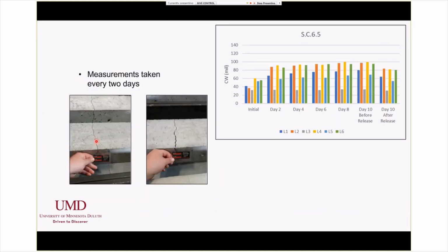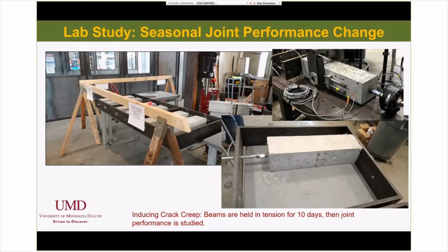The cracks were not that wide initially. We chose this picture just to show the crack. We used a flexural load to crack this beam at 18 hours after the construction. You can see we developed this facility where we could apply tension on 6 beams together, for as long as we want. For this particular research, we applied tension for 10 days.